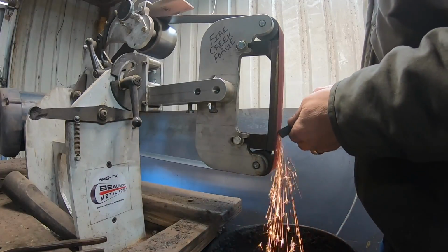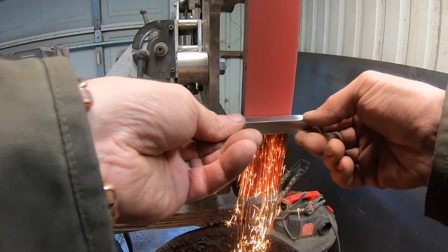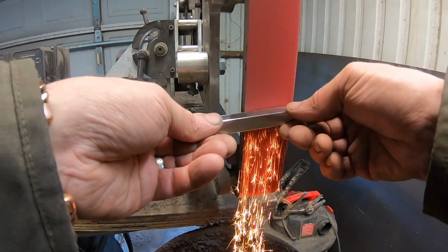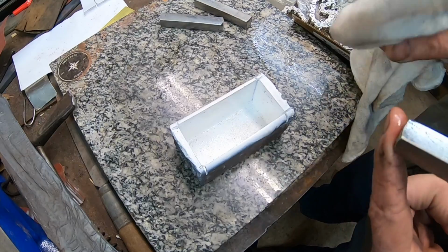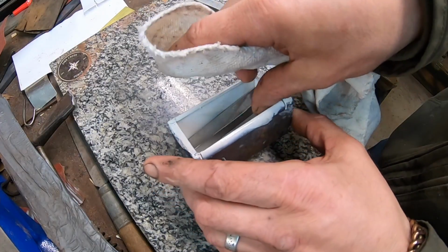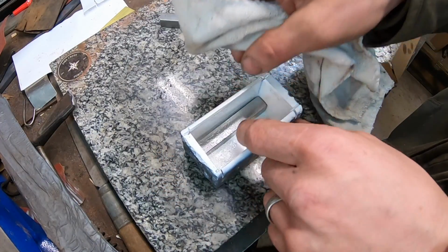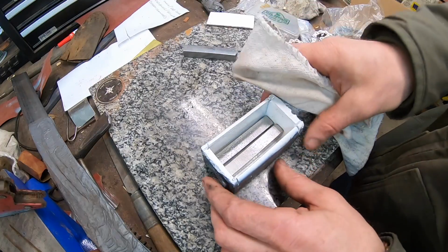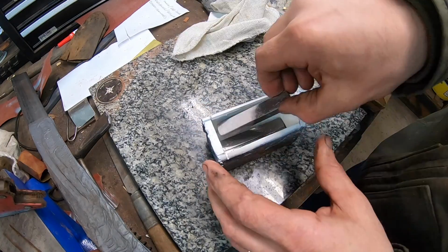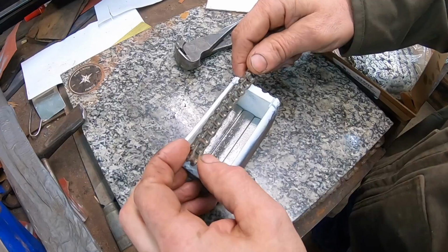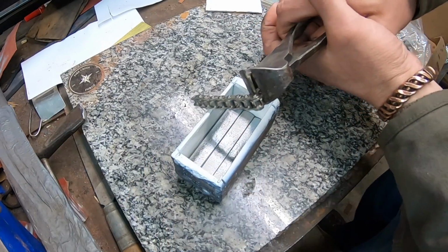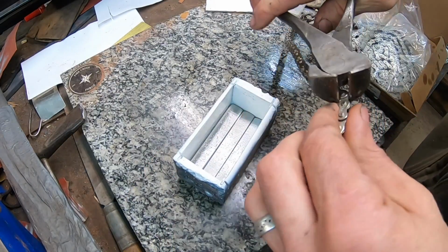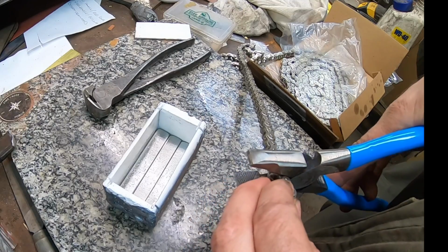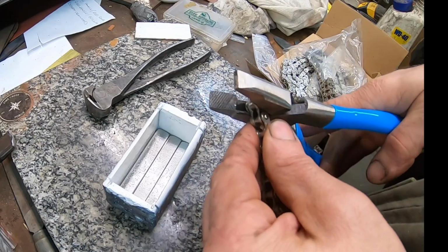So I need to forge that into a square bar of specific dimensions, and I'll need 3 of those to put in the bottom of the canister. Once this is all forge welded together and forged down into a blade, this will constitute the edge of our knife. For the rest of the blade, I want some cool pattern welded steel using this nickel plated roller chain,